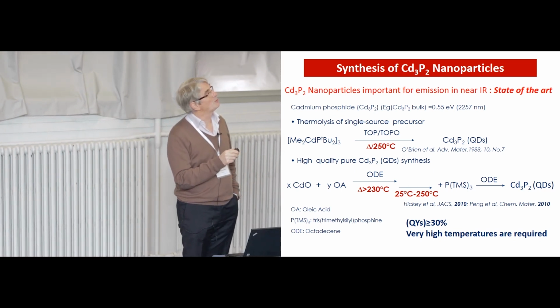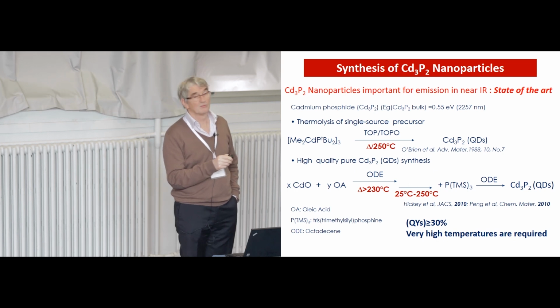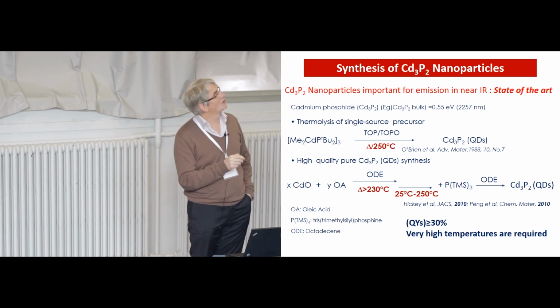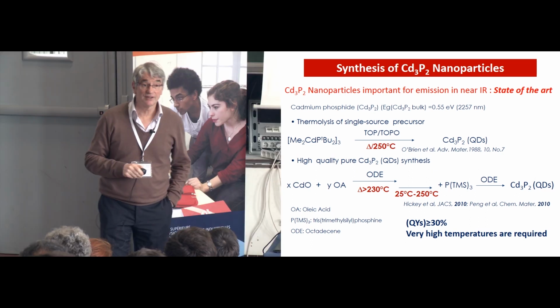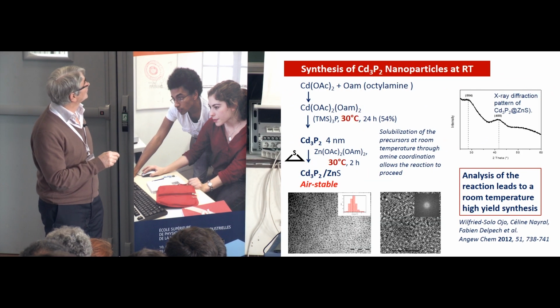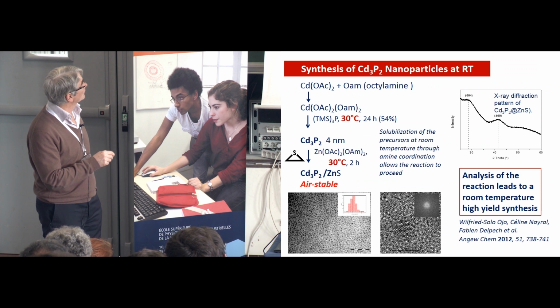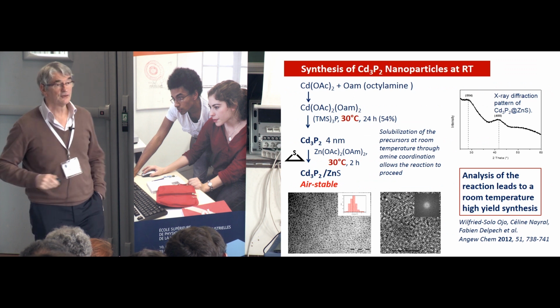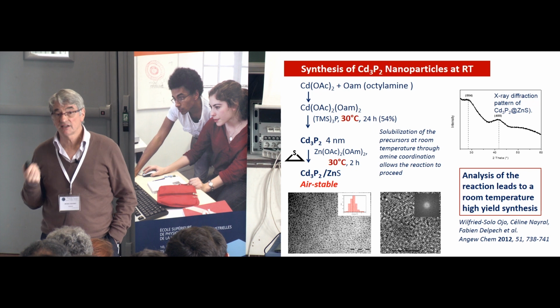that if you solubilize your cadmium acetate before the reaction, you have a soluble complex containing acid and amine, and that you can feed with your phosphorus precursor at room temperature, and you get crystalline cadmium phosphide.